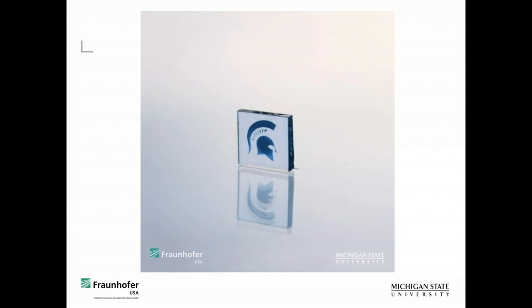They wanted the Sparty Head diamond. You can add different process gases or impurities when you grow diamond to change the color. While we use boron doped diamond for the rest of this presentation, when you grow single crystal boron doped diamond, it's blue. When you don't add any boron or another impurity into single crystal diamond, it's clear. Sometimes it's yellow from the nitrogen content. In general, this was a single crystal diamond layer grown with no dopant or impurity, and then we structured a layer on top and deposited boron doped diamond,